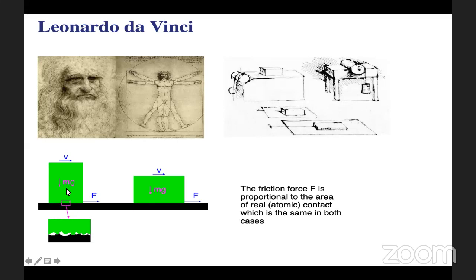For example, here you see that there are two blocks. They have different apparent areas of contact. This block has a smaller apparent area of contact, and this block has a bigger apparent area of contact. But the weight or the mass of them is the same. So the frictional force that is required is also the same. But people will think that the frictional force in both the blocks will be different. But as the frictional force is dependent on the area of real contact, and the area of real contact depends on the normal load, we see that both blocks will start to move at the same frictional force.